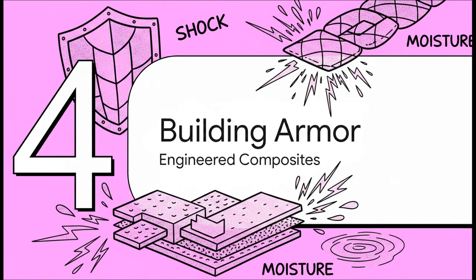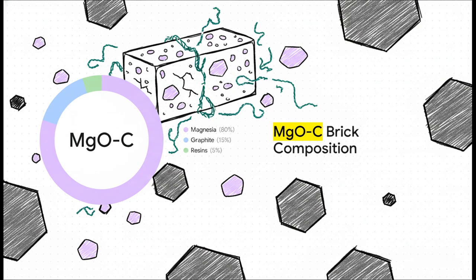Engineered composites. To build a virtually indestructible material, engineers rely on the industry standard MgO carbon brick. By mixing about 80% magnesia with 15% graphite flakes and 5% resins and antioxidants, we get an incredible composite. The rigid magnesia grains are essentially wrapped inside this flexible, interconnected carbon skeleton. This carbon matrix gives the brick what's called pseudo-ductile failure. That means it can flex just a little bit rather than shattering, which grants it unbelievable thermal shock resistance.